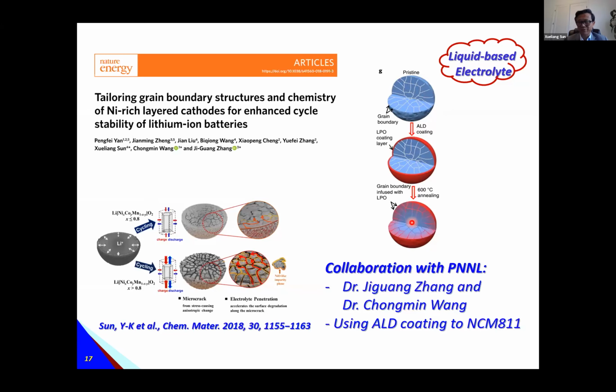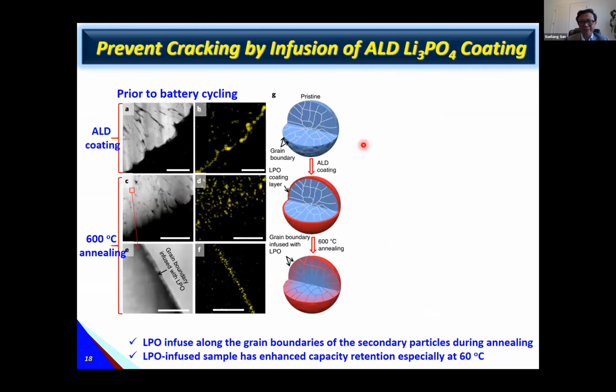to address this problem. So we're using ALD to synthesize lithium phosphate on the NMC 811. After coating, you can find the signal of phosphorus on the surface. After annealing, the coating material penetrates into the grains and then stays in the grain boundary. You see the phosphorus signal on the grain boundary. So using this procedure, the material is already in the grain boundary.